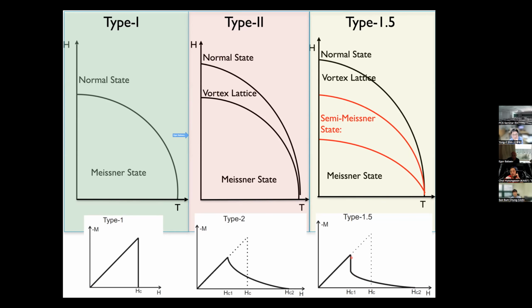And then there are first-order magnetization curves. In that case, it is a first-order phase transition at the first critical magnetic field, where the system goes into macroscopic phase separation into vortex clusters and Meissner state.